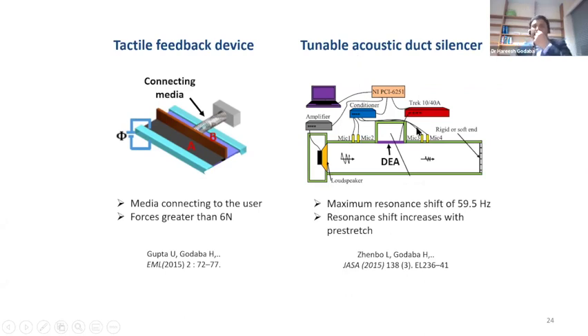And here, in another study, we have pursued applications of these dielectric elastomers to make a broadband acoustic duct silencer. Here we covered a Helmholtz resonator with a dielectric elastomer actuator that is pre-stretched with electrodes coated on both sides. Now what happens is when you have a pre-stretched membrane and you apply voltage, the electromechanical stress that is generated counteracts the mechanical stress, and the membrane can become soft. By this, we can tune the apparent stiffness of this membrane. And just by doing this, we can change the resonance frequency of this type of duct silencer.